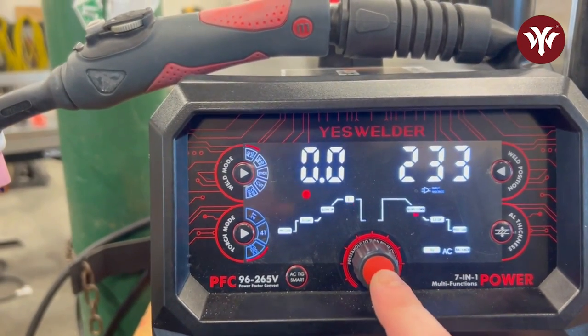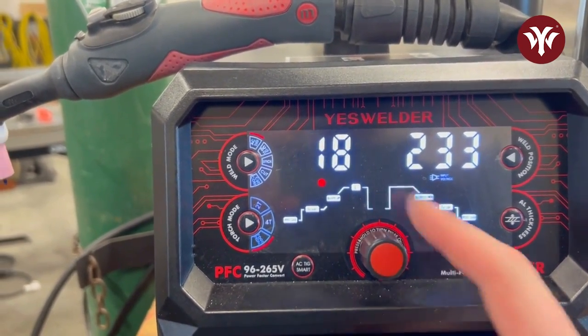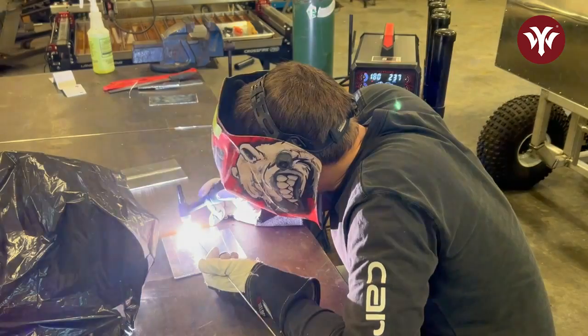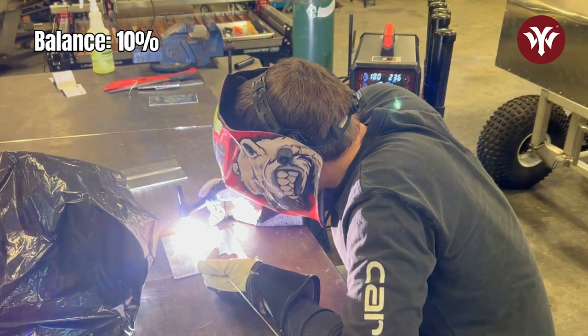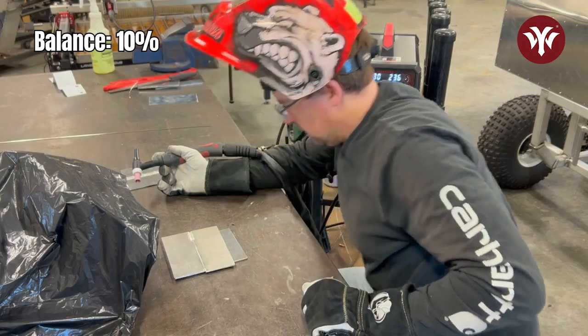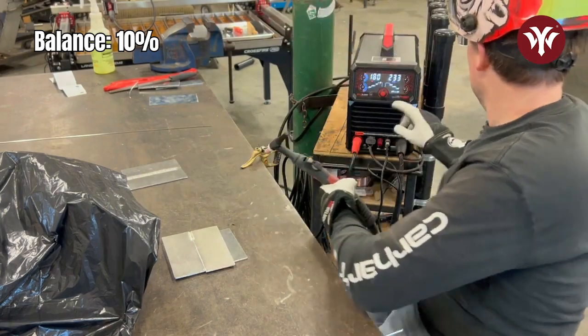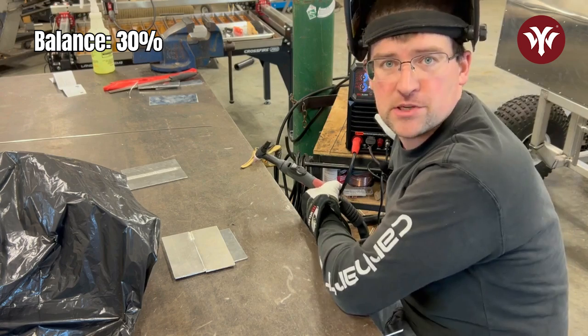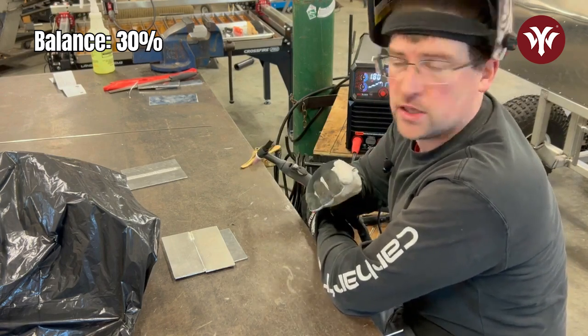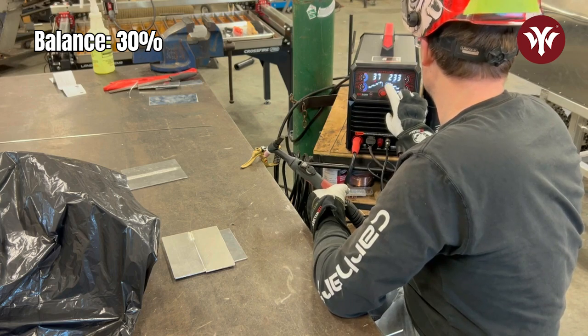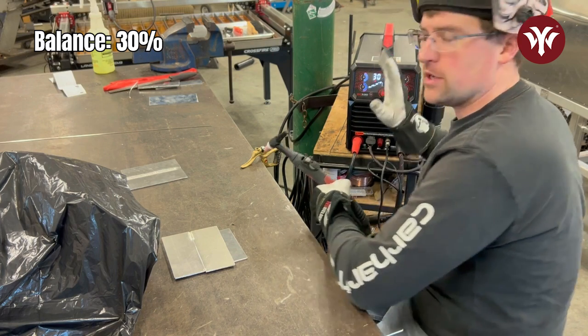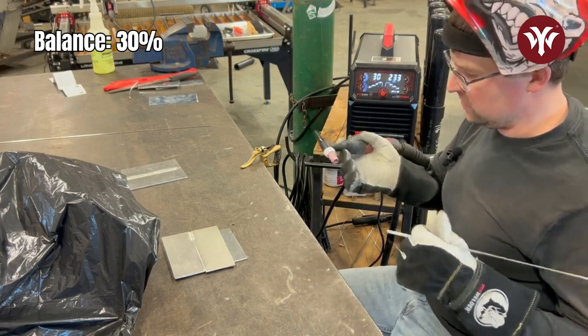Okay, for this first demonstration here, let's go to balance and let's turn that down to 10. So right away I'm noticing a little bit more contaminant on top of the weld bead here. And I can also feel with my foot pedal that it's taking much less current to operate. Okay, that was not very pretty. Now let's set balance to 30%. We'll put a nice bead in the center and then we'll go real high. 30% is a nice setting. Let's test that out.